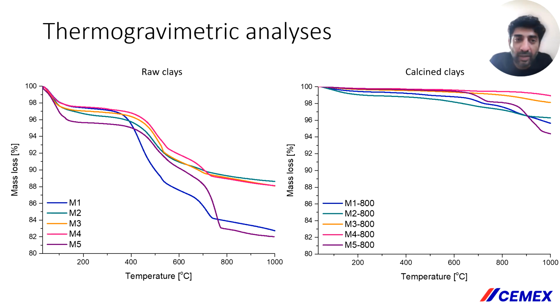Right, we carried out thermogravimetric analysis on the raw clays, which basically corroborates the mineral phases identified in the XRD patterns of the raw clays. Mass loss in the temperature range 400 to 600 degrees Celsius for all 5 raw clays is concurrent with the presence of kaolinite. Then you have the mass loss between 600 to 800 degrees Celsius, which can be attributed to carbonate minerals, including calcite and or dolomite. One thing you'll notice is the total mass loss at 1000 degrees ranges between 11 to 18%, depending on the clay, highlighting the differences in quantities of the minerals present.